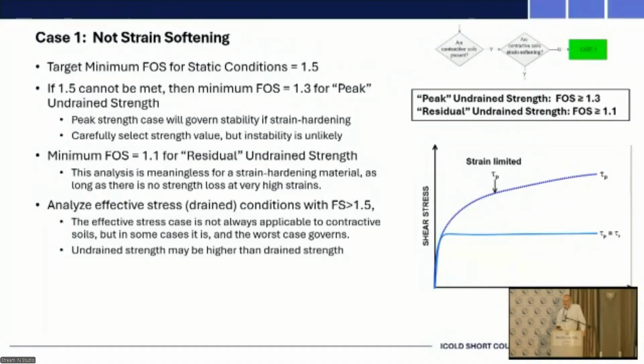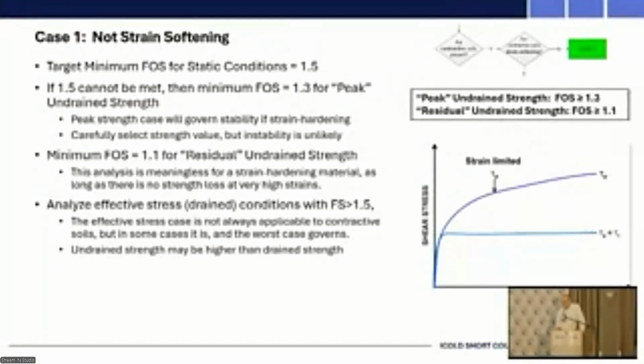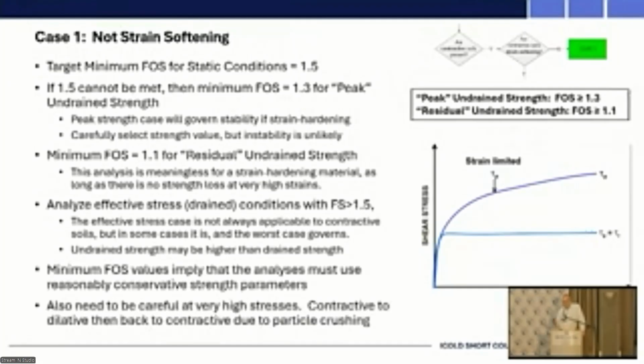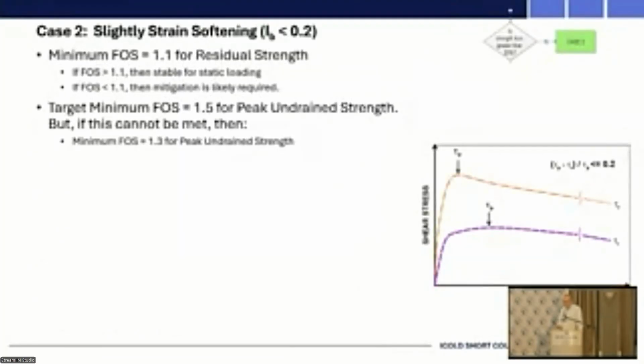In this case, the residual strength or the post-liquefaction or the large strain case isn't really relevant because you never reach a residual because you don't have strain softening. So by definition, that analysis isn't really useful. Just keep in mind to make sure your strength parameters are appropriately conservative, and then also be careful at high stresses because you could have some particle crushing, which would also lead to contractive behavior. And so at high stresses, be careful about applying this.